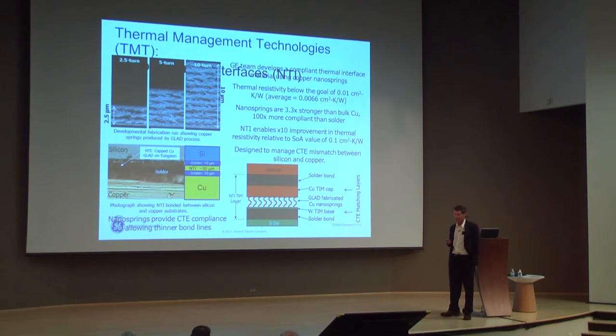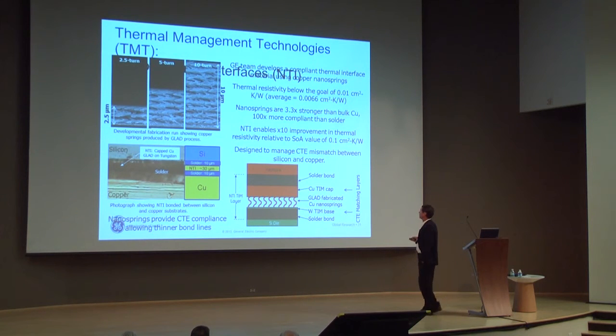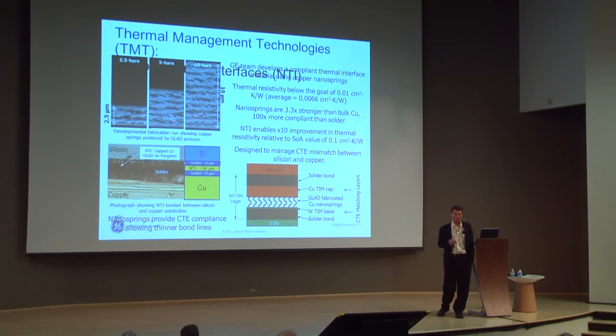It can be a limiting factor in what you can do. This is a problem with what we call the thermal management technologies where we're using nanosprings. What the problem is in a lot of power modules is that the silicon dies have a different thermal expansivity than their heat sinks, which tend to be metal. And after a while, you wind up with big problems at the interface. So that can be a life-limiting problem.